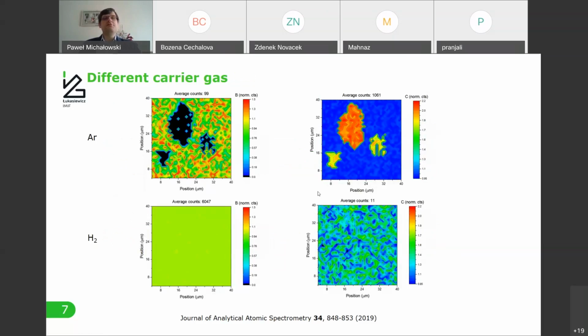So first, when we consider the different carrier gas, you can see that when we compare the boron distribution or carbon distribution within a layer, there are significant differences. So first of all, the boron distribution is very inhomogeneous if argon was used as a carrier gas, and there are even some places where no boron nor carbon can actually be detected.